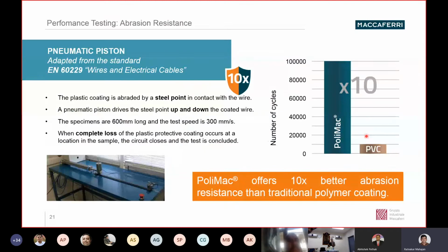First is the abrasion resistance. In the test carried out on the PVC coated wire and the PoliMac as per this EN 60229, we found that the PVC could, let's say, offer some resistance, but PoliMac is offering roughly 10 times higher resistance. So this is, I would say, having 10 times better abrasion resistance than the traditional polymer coating, which is usually PVC.